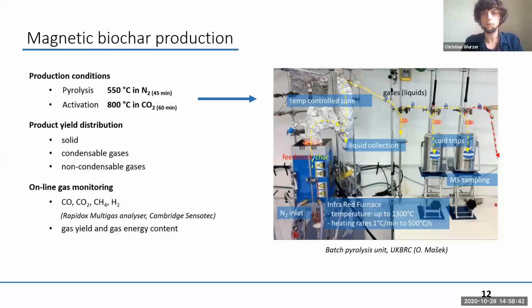On the right, you can see the reactor we used. It's an infrared heated reactor. The gas exhaust is flown through 4 condensation traps to remove the condensable fractions, or the tars, before the gas fraction is analyzed by our online gas monitoring.